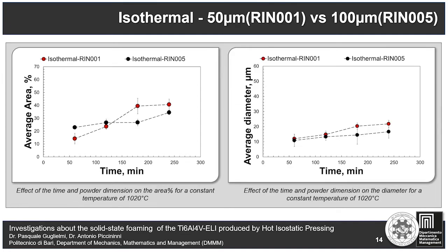Considering the same type of heat treatment, another interesting result comes from the comparison of the two different materials investigated. If we observe the comparison proposed for an isothermal treatment, the two materials seem to show, at least for the tests up to 4 hours, a similar behavior. A slightly higher porosity was recorded in correspondence with the maximum size of the titanium powder equal to 50 micron.